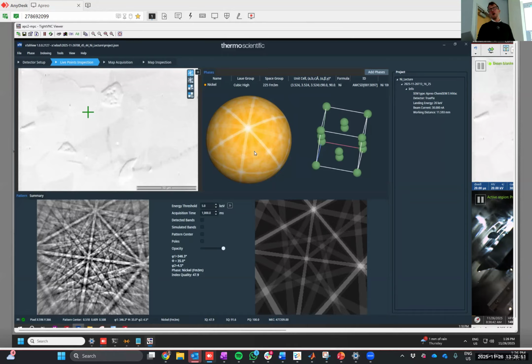And the surface is, metallographically, not very smooth. This is showing you topography and a backscatter, but it's very crystalline. So we polished it carefully, and then there's slight roughness because different grains have different polishing rates in that sample. This is the demo. This is the one that always works because I don't want to mess stuff up. It will hopefully look like this if you do your own experiments, but just to temper people's expectations, we spend a fair bit of time dealing with sample prep, and we have lots of experience in that space.